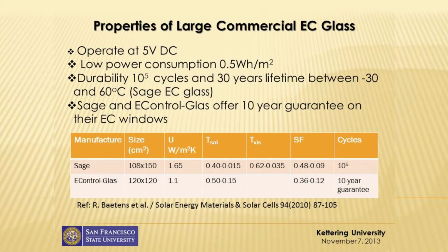Now, properties of large commercial electrochromic glasses. It operates at 5 volt DC. That's the maximum value, but for the smaller size, you can use 1.2 or 3 volt. Lower power consumption, about 0.5 watt hour per meter square. Durability, more than 10 to the 5 cycles, and 30 years lifetime. These are the values that Sage Glass Company mentioned in their report. So it's 30 years when they operate from 30 to 60 degrees centigrade. Sage and E-Control Glass offer a 10-year warranty on their electrochromic windows.